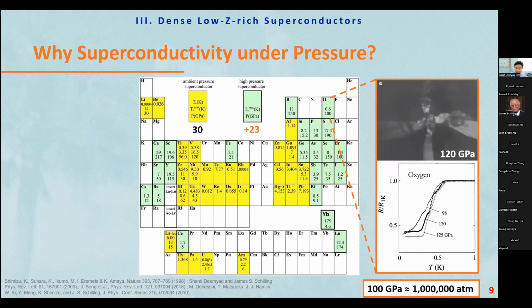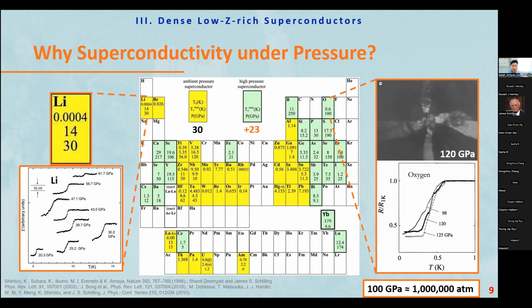For example, oxygen is not an ambient-pressure superconductor, it's just a gas. But when you apply pressure, it metallizes and it even becomes a superconductor at 120 GPa. So the oxygen you breathe, the normal life surrounding us, becomes a superconductor under pressure. That's amazing.